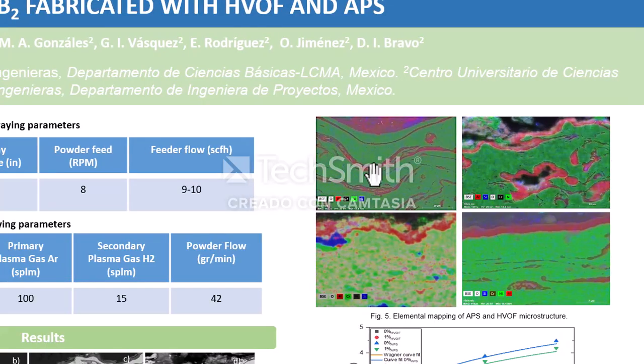The element mapping shows that aluminum, oxygen and silicon are distributed in the samples after 100 cycles. These elements show that the APS sample experienced more oxidation than the HVOF sample, and the silicon seems to segregate to the surface, possibly forming oxide.